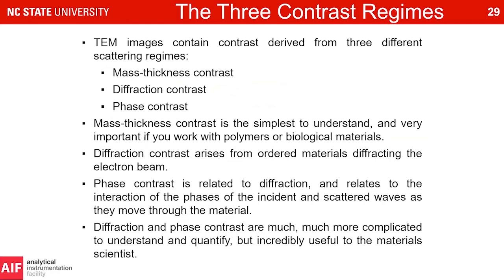TEM textbooks typically discuss contrast regimes: mass-thickness contrast, diffraction contrast, and phase contrast — and STEM people add Z-contrast or HAADF contrast. If you're working with polymers or amorphous materials with only short-range order, mass-thickness contrast is the most important contrast mechanism — meaning what makes something dark or bright in our image. For amorphous materials, you can get away with really only considering mass-thickness contrast.